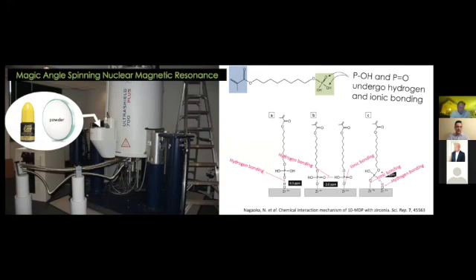And you can do this based on a marker element that they pick. And I think in this study, they picked phosphorus as a marker element. And they could tell the distance between the phosphorus and the zirconia atoms, and if they could approximate that distance, they could tell what kind of bonds were occurring. So they hypothesized that there are ionic bonds or hydrogen bonds that occurred between MDP and zirconia.